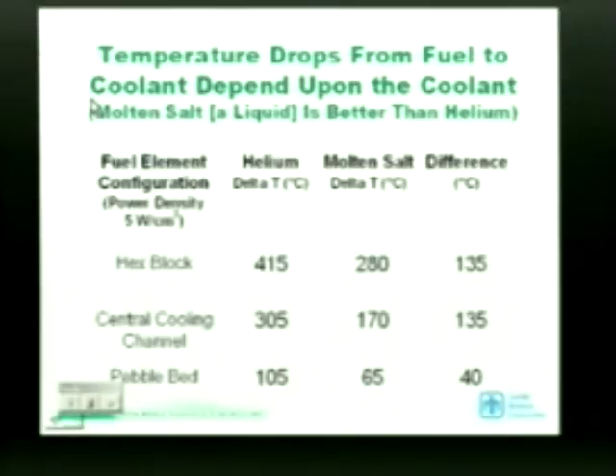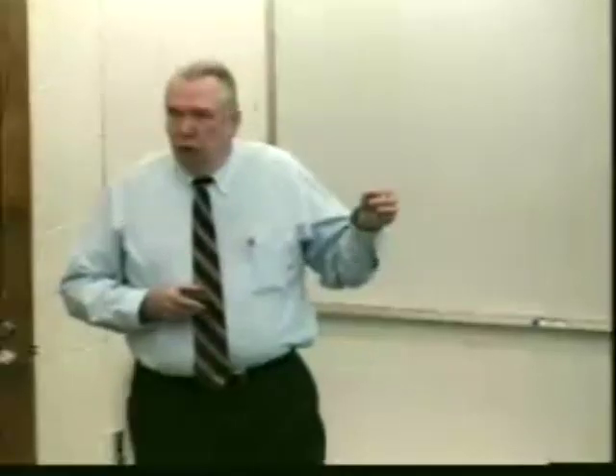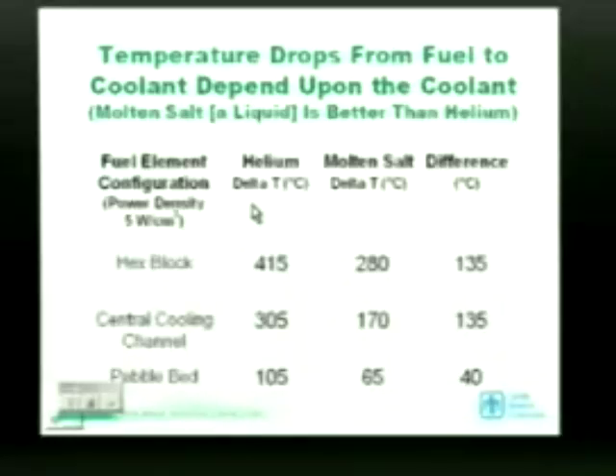Now, let's take a look at what the implications are of using a liquid coolant with a high-temperature fuel. The important point here is that the temperature drops from fuel to coolant depend upon the coolant. Here we show a number of fuel element configurations: hexagonal block, central cooling channel, and pebble bed. Here we show the temperature drops between the very hottest point in the fuel and the liquid coolant, or the gaseous coolant, whatever the coolant is. And for a high-temperature reactor with a hexagonal block, the maximum temperature drop, delta T, is 415 degrees C. That is, the microsphere of uranium at the center is 415 degrees C hotter than the helium in the middle of the coolant channel. In comparison, if we put in molten salt in the same type of fuel element, the temperature difference between the hottest point in the fuel and the coolant is 280 degrees.